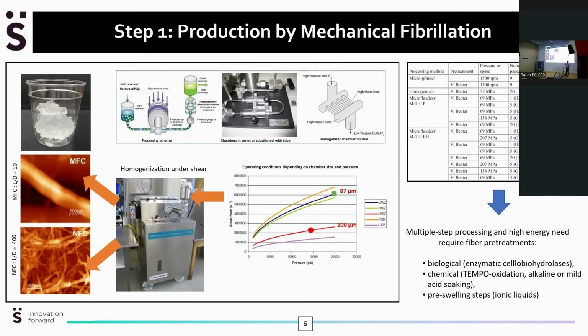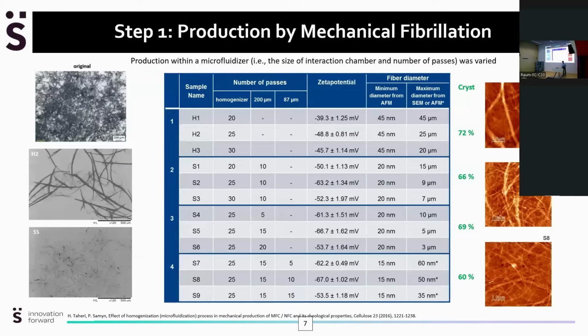Through pre-swelling, you can open the structure and weaken the interactions between the cellulose fibrils in order to have a more fluent fibrillation. One technique that we use here is interaction with ionic liquids, where after the processing, these ionic liquids can be recycled again, or eventually direct processing into nanocellulose composites can be done in this ionic liquid phase.